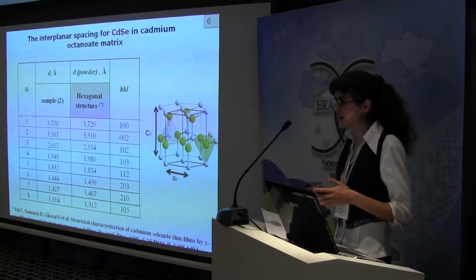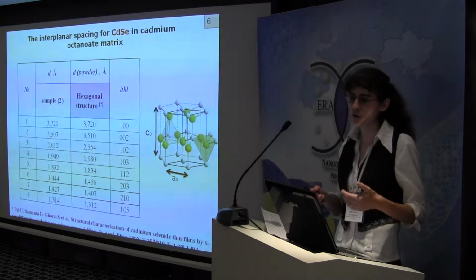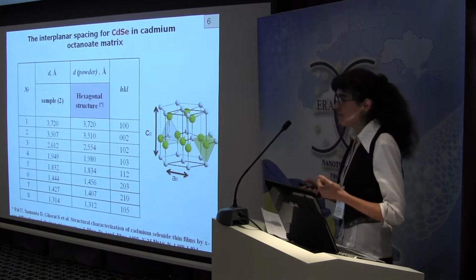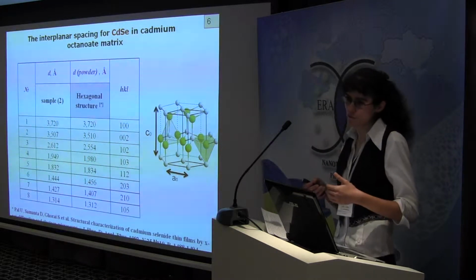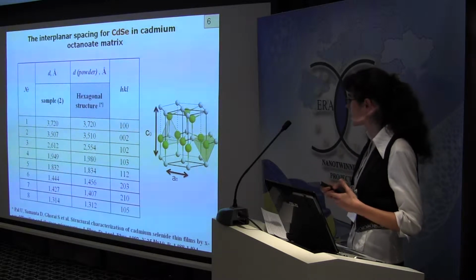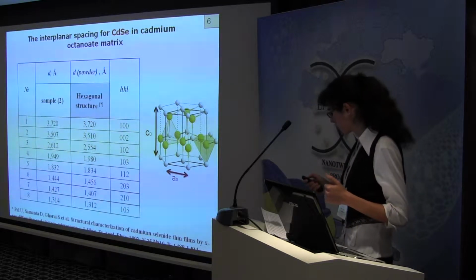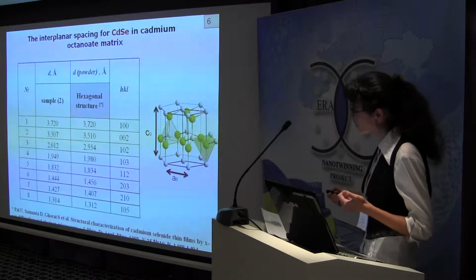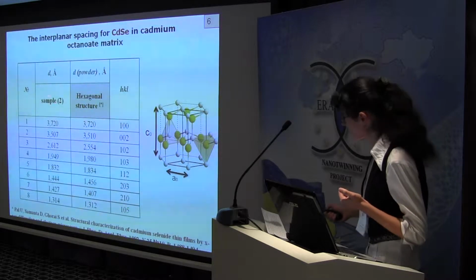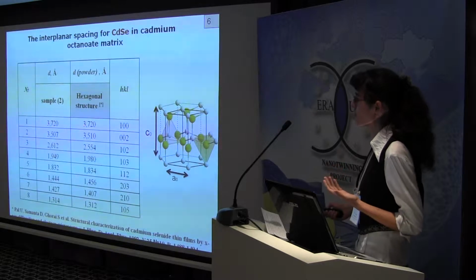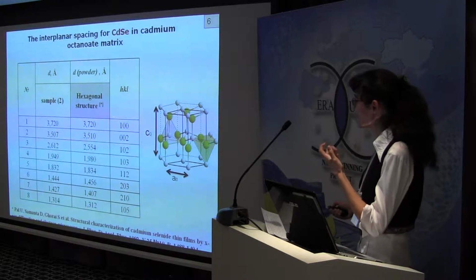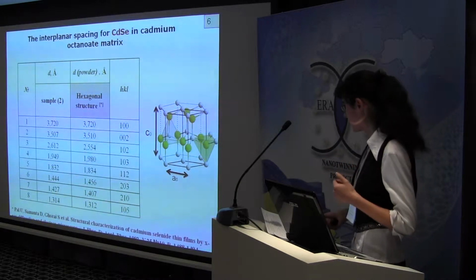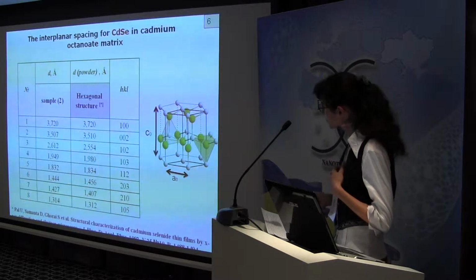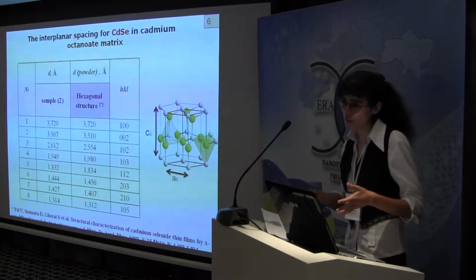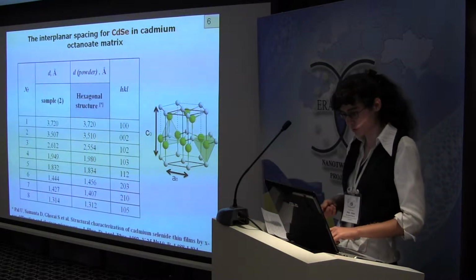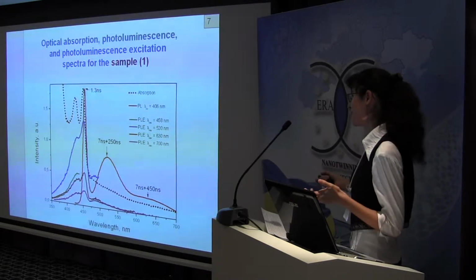It was shown that cadmium selenide nanoparticles can form zinc blende, rock salt or Wurtzite crystal structures. Electron diffraction confirmed the crystallinity of our nanoparticles and their composition, nanocomposites. From electron diffraction, we calculate interplanar spacing for cadmium selenide. The obtained values for sample 2 are in good agreement with those obtained earlier for hexagonal structure. Let's see below the reference. And so the crystal structure for our nanoparticles is close to hexagonal structure, Wurtzite structure.